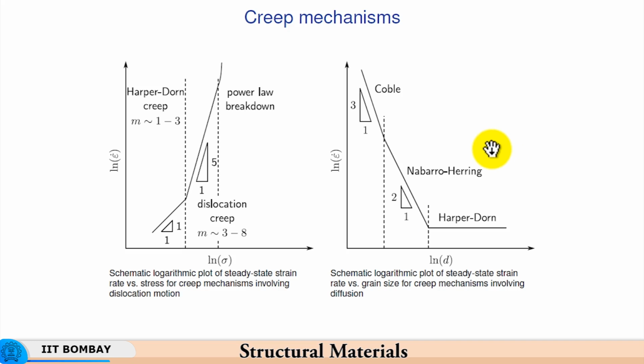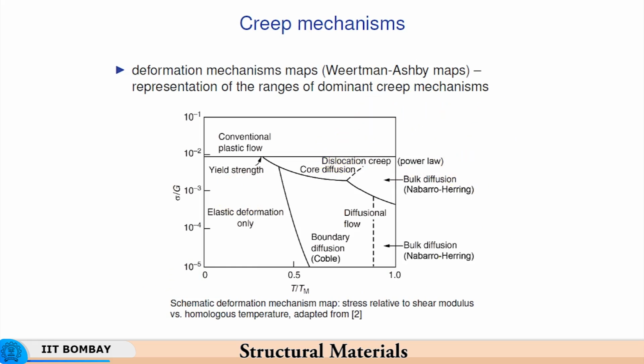So, that is the reason why the diffusion controlled processes, Coble and Nabarro-Herring creep, get affected the most, whereas Harper-Dorn creep, which is independent of the grain size, continues irrespective of the grain size. So, here we have the Ashby-Weertman maps, where we lay out different mechanisms.